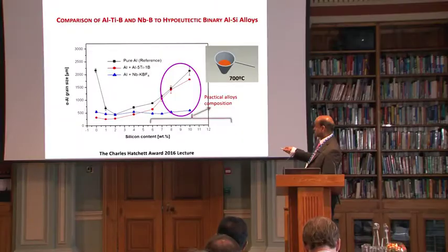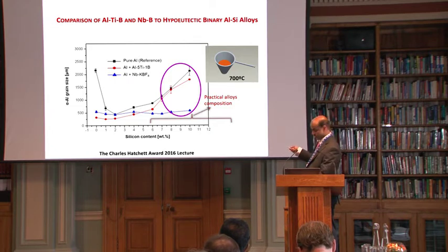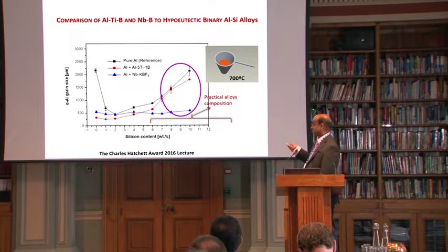Inoculants are already widely used to refine the microstructure of castings, and these are normally based on aluminium-titanium-boron compositions. A drawback of such inoculants is that silicon reacts with the titanium, reducing their effectiveness, especially at silicon levels above 6%. The present work has demonstrated that niobium-boron additives can be very effective inoculants, as they do not interact with silicon to cause the issues already mentioned.